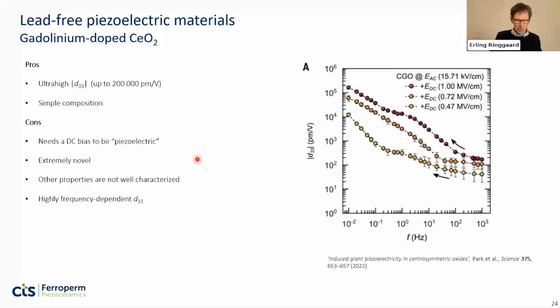Then just a few words about these electrostrictors. There was actually a webinar mentioning quite a few details about that in the spring series by Vincenzo Esposito. But in short, potentially you can obtain a very high d33, extremely high, up to 200,000 picometer per volt, but generally at very low frequencies. So we are luckily in a project where one of the aims is actually to take these very nice properties of these electrostrictive materials and take them to higher frequencies than just a few tens or hundreds of hertz. So we hope that we can give you news about that within the next few years.